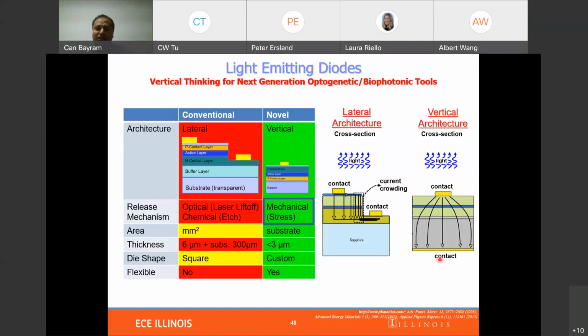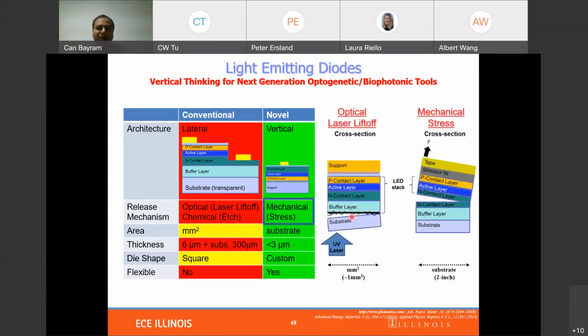So it's important to have vertical structures where the current can spread, the illumination is more uniform, and the heating is much, much less. And the typical way of removing the substrate is through laser liftoff, where the laser is coming in through the transparent substrate, and the buffer layer, the gallium nitride type structure, becomes a gallium melt and nitrogen popping off the substrate. And this really limits the chip size as well as the yield.